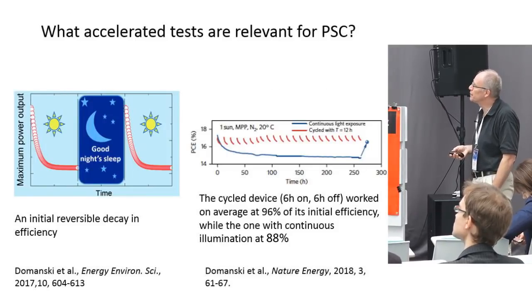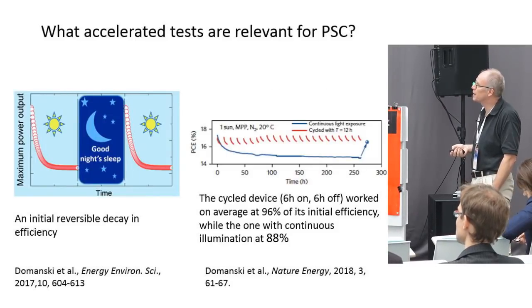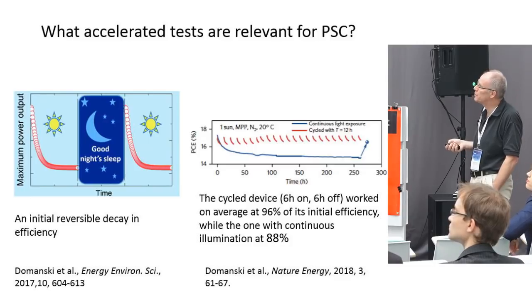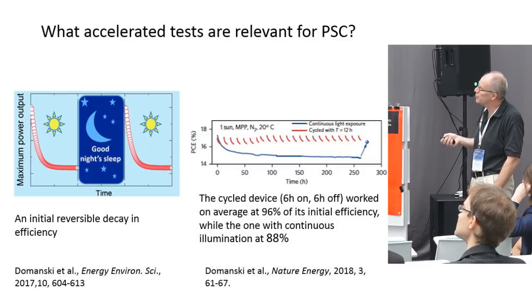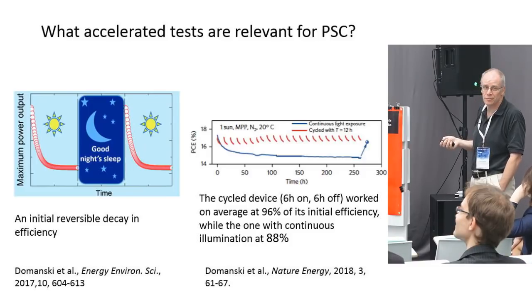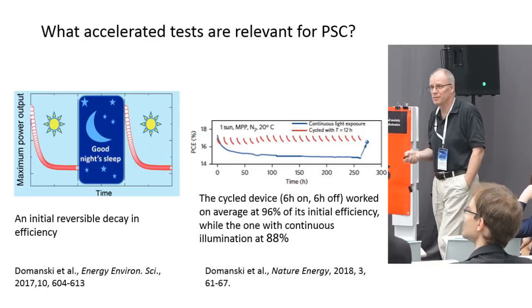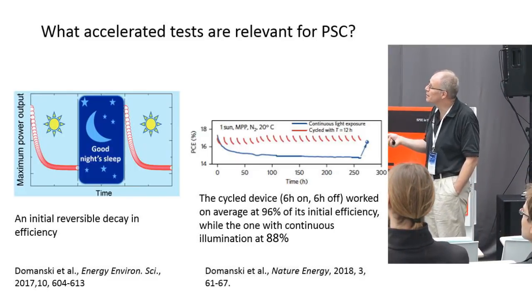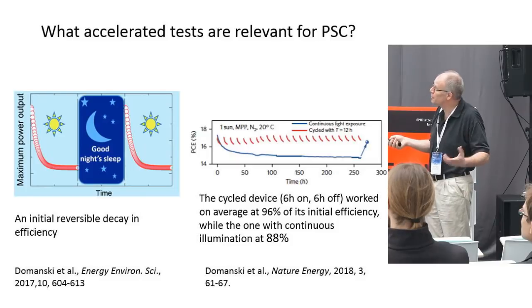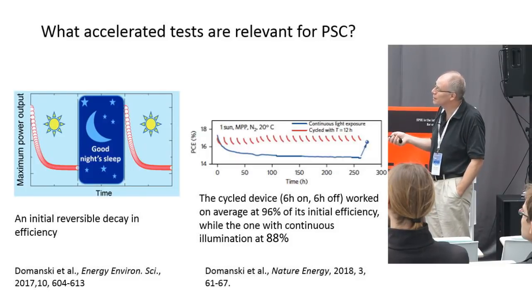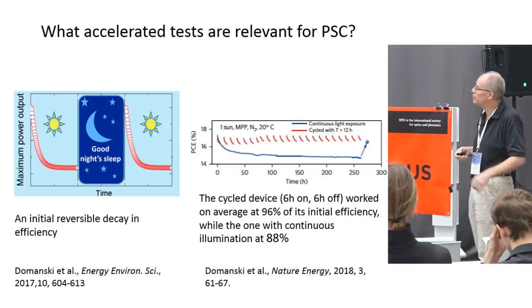So another exciting thing which comes up sometimes of surprise is that what we saw in our stability data is that in the first minutes there is a drop. And then we thought this is a degradation and it stabilizes. But then we saw that if it takes a rest, a good night's sleep, we are back next morning where we started. So this is reversible. And also something of research to look into. What is this initial degradation, which is not a degradation in a way, because when it rests, it comes back. So it's something, ionic motions and so on.